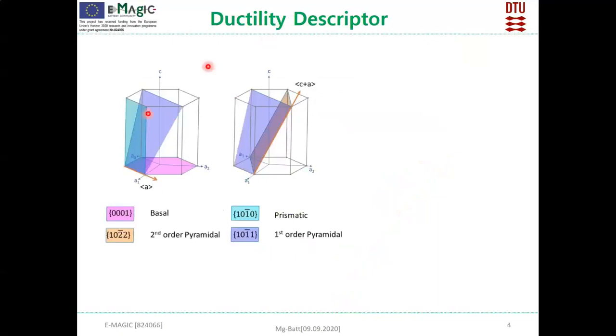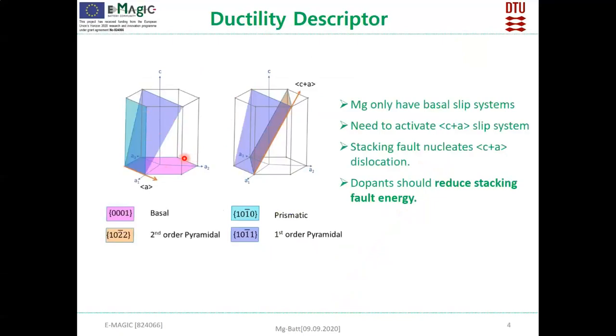Here, the main reason for the poor ductility is the insufficient number of slip planes for deformation. What you see here are the different slip systems available in HCP magnesium, and for magnesium at room temperature only basal slip systems are available. But in order to accommodate the strain along the c axis, we need to activate the c+a slip system. Several studies indicate that the stacking fault in the structure can nucleate the c+a dislocation, which in turn activates the c+a slip system.